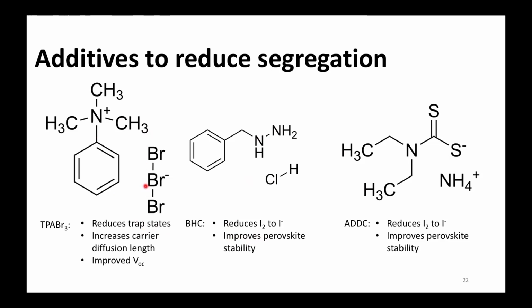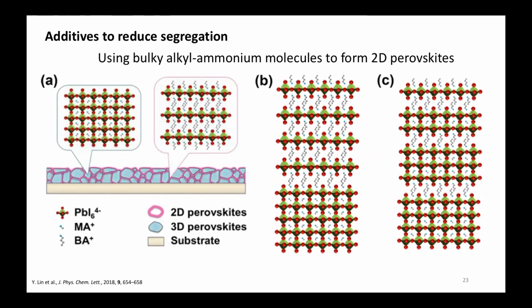You can substitute the Br- for Br3-. You basically improve the binding. So you have fewer defects if you take this additive. You can use the alkyl ammonium additive. So you use bulky alkyl ammonium molecules. This would be a bulk crystal, just a normal perovskite structure. But in between the crystals, these alkyl ammonium molecules end up there. And they can interact. So they form the interface between two grains.